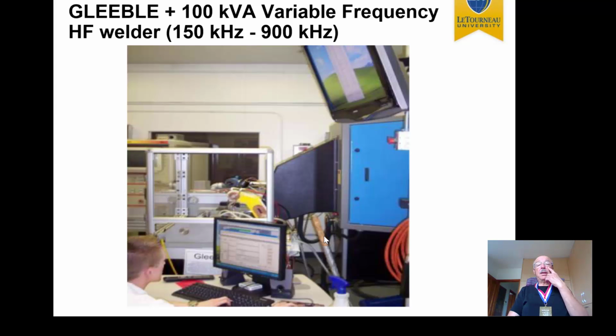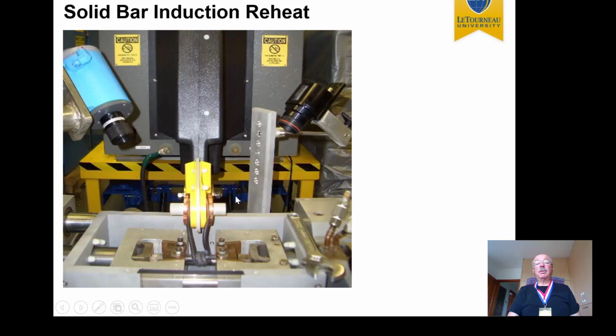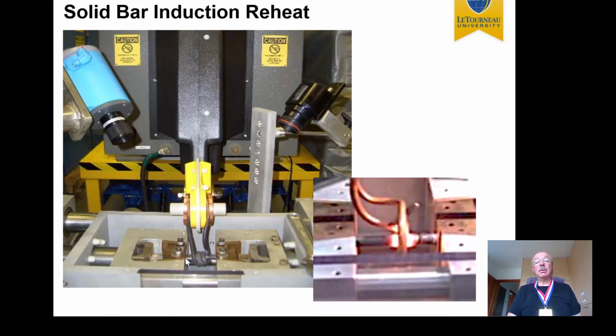So here is the experimental setup. You can see here a modified Gleeble 1500 with a 100 kVA high-frequency welder, and basically the Gleeble provided the mechanical cycle to push the two edges together, while the high-frequency welder, which came in perpendicular to it, provided the heating. And this really was a very difficult undertaking, but we wanted to replace the resistive heating of the Gleeble with this inductive heating coming from a really high-power high-frequency welder. And you can see we had a multitude of thermal cameras looking at this. We measured not only temperatures but deformations and rates. So it was a highly controlled experimental setup.